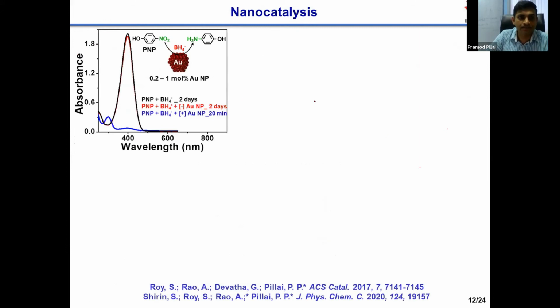So these are the results. When we don't have any catalyst, the spectrum that we obtained is the black one. We don't see any change in the reactant peak. And when we have a nanoparticle with a negatively charged surface, that means unfavorable surface chemistry, there is negligible catalysis. But the moment we use a positively charged nanoparticle with a favorable surface chemistry, within a few minutes, we see that the complete reactant has converted into the product.